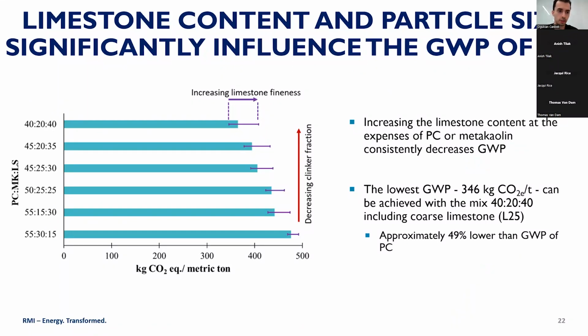So this figure shows how the global warming potential of LC3 changes with respect to varying proportions of the components, Portland cement, metakaolin, and limestone, also with respect to limestone fineness. Just to summarize, what I want you to notice is that increasing the limestone content at the expense of Portland cement and metakaolin decreases the global warming potential of LC3.